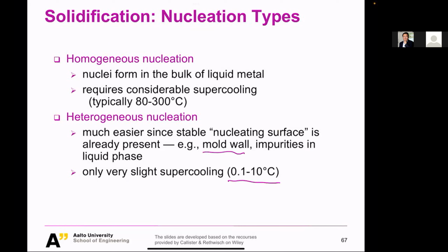So this is so-called heterogeneous nucleation, and the supercooling temperature is really small. You just need something like 0.1 to 10 degrees C, and you would already develop very many nuclei for this heterogeneous nucleation. All right, that was a rather simple description of the mechanism. As I said, just get a sense of it. You know why you are having supercooling, superheating to help the transformation process.